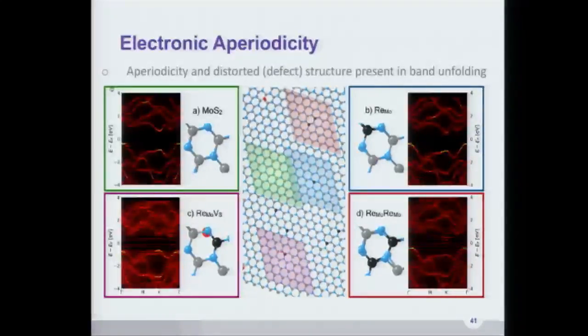What we do is take those atomic coordinates, and we also first predict for these same systems, same defects, what you would expect as the electronic structure. We unfold the bands to see where exactly you would see the different defect positions. But with the same system, using the experimental atomic coordinates, you see that there's actually a whole bunch of shadow bands, and that you see in the electronic structure a lot of non-equilibrium features show up. And this is because when they experimentally measure this, they see that there's a lot of Z variation. They see there's a lot of local disorder created by a defect. And actually, the system doesn't relax down to what you expect will be the equilibrium configuration once you introduce the defect. So this is an inherent assumption in theory that I introduce a defect or an imperfection, and then the system relaxes.